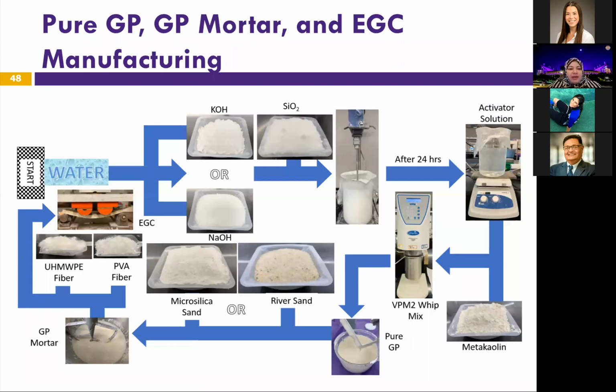Okay, so how do we make the EGCs? If we look at this chart schematic, we start by mixing the DI water with the activator solution, either sodium-based or potassium-based with silicon dioxide, and we mix it at low heat for 24 hours until it becomes clear, and you can see right here. Once that happens, we start adding the metakaolin or the metakaolin fly ash, and then we put it in a whip mixer